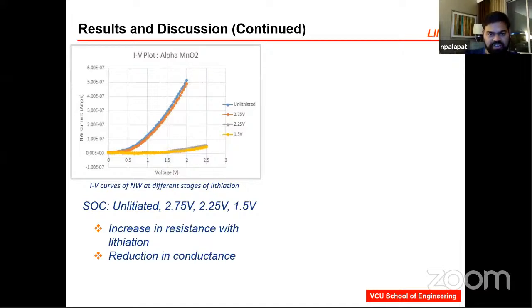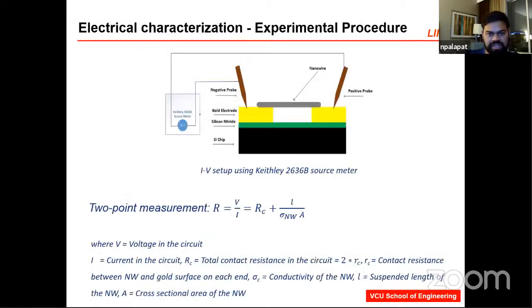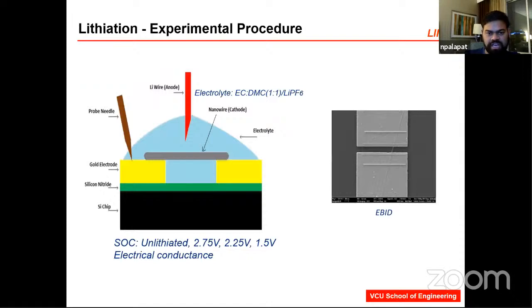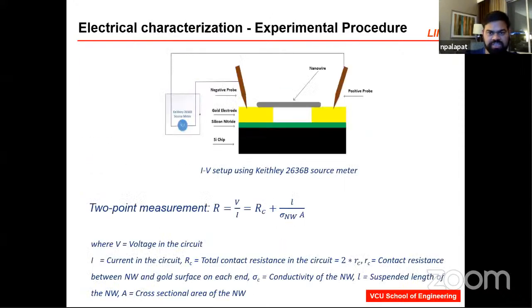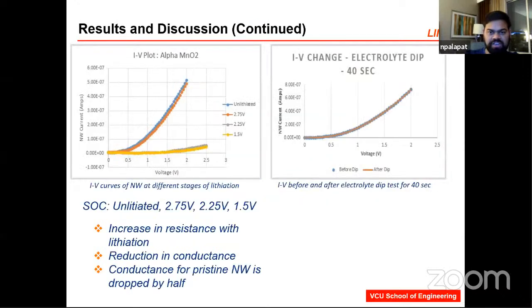Now, there must have been a question. If I go back, I talked about in the experimental setup, in the lithiation itself, there is an electrolyte involved. Now, the electrolyte can impact the nanowire technically. But the beauty of the experimental setup is that when we did just the electrolyte measurement, we did not really see any change before and after on the nanowire. So thereby we eliminated that the electrolyte can cause any effect on the nanowire.